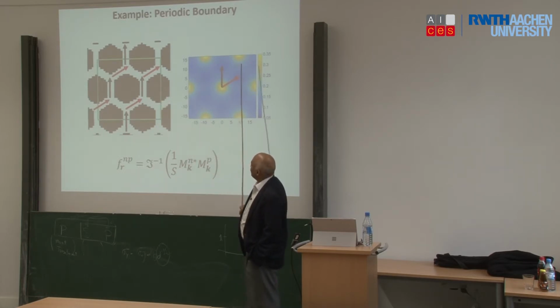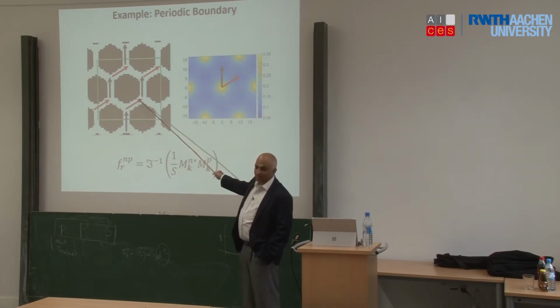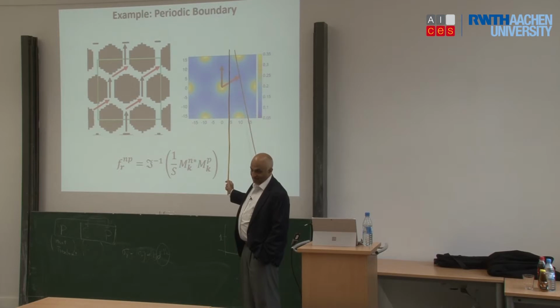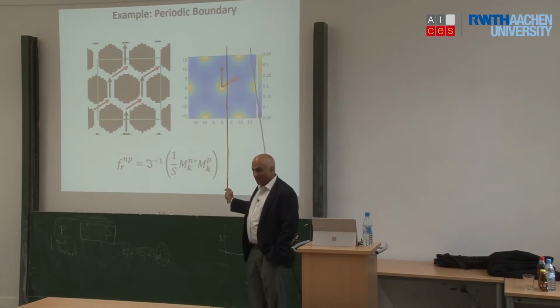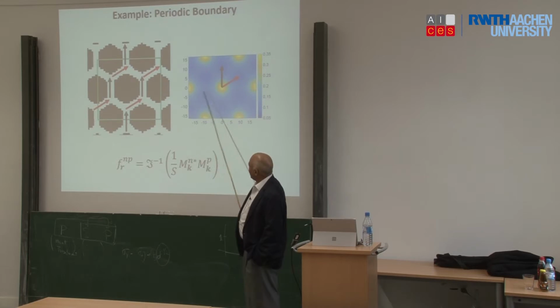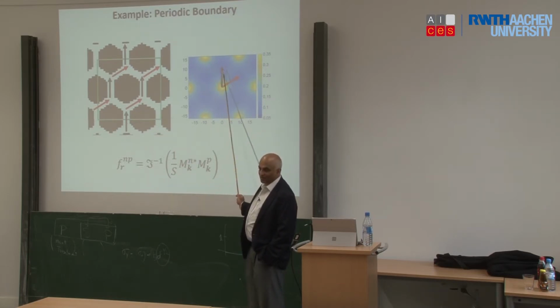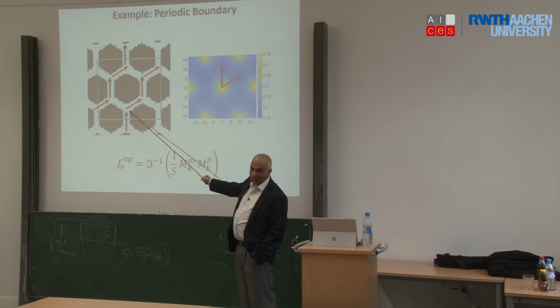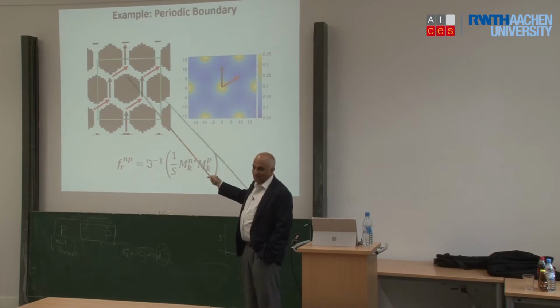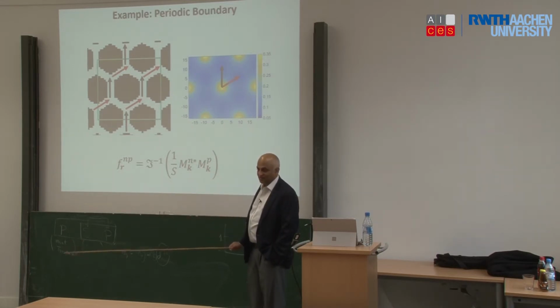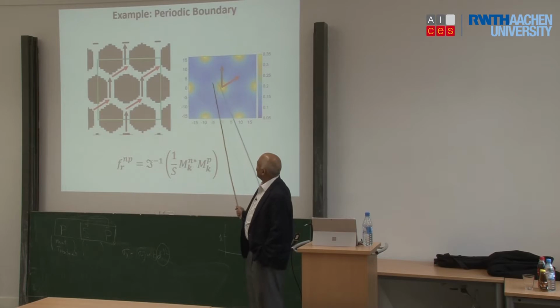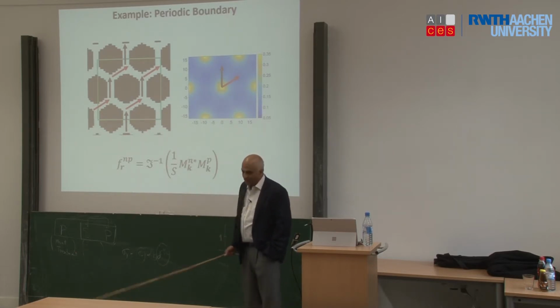The reason I'm saying that is we also spent quite a bit of time showing that if you give me this and don't show me this, I can reconstruct this voxel by voxel from here. So the point is there's a lot of information in this, and in fact we argue that there are a few cases where we are not able to reconstruct, because the reconstruction is an inverse problem, right? I have the 2-point statistics, now I want to know what the original one looks like. There are a few cases where we couldn't do the reconstruction, but in over 95% of the cases we can do an exact one-to-one reconstruction, right? So the main point is there's a lot of information that it carries.